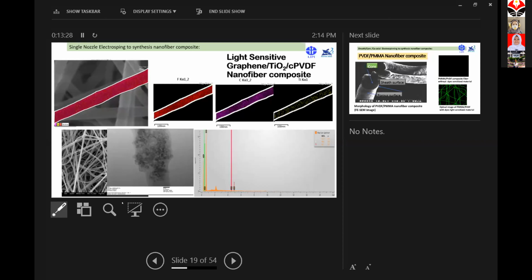By using SEM EDX, scanning electron microscopy EDS, you can see here the distribution of fluorine atom in the nanofiber. Here you can see the carbon, and then we can see the titanium distribution in the nanofiber composite. The yellow point is titanium. Also, when we see in the transmission electron microscopy, we can observe the nanoparticle in the nanofiber composite.